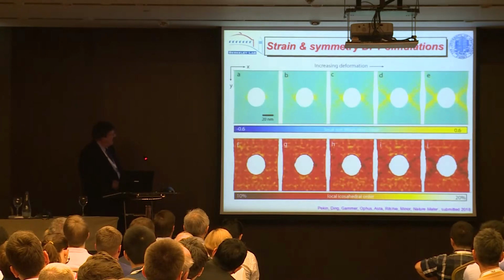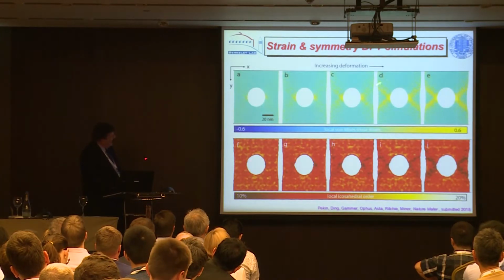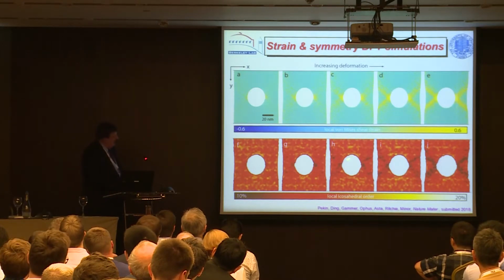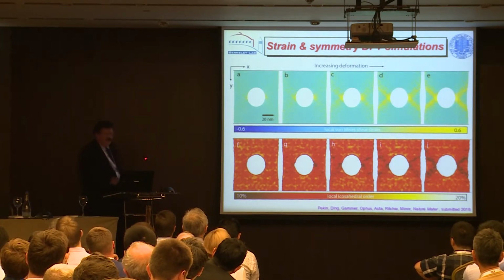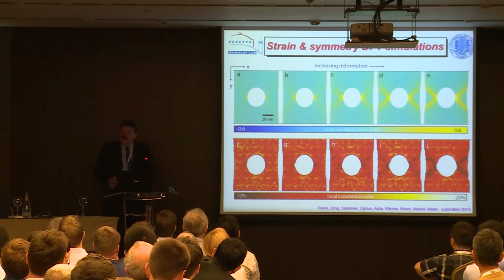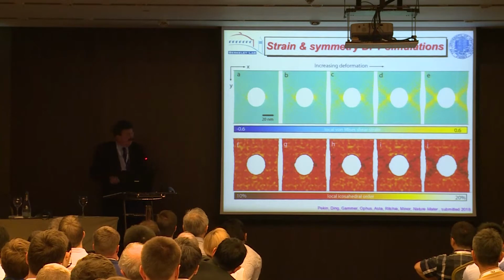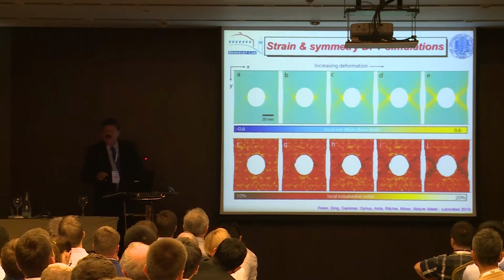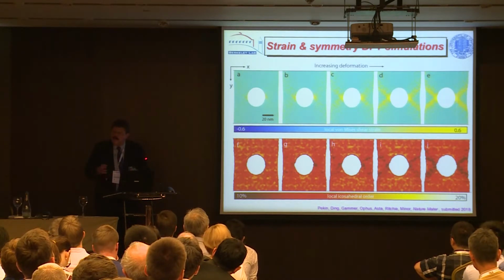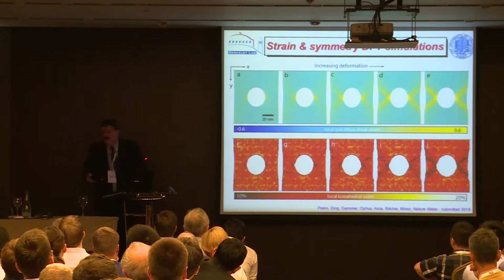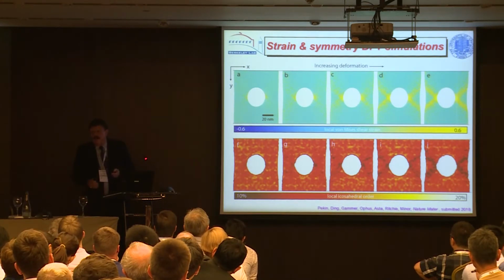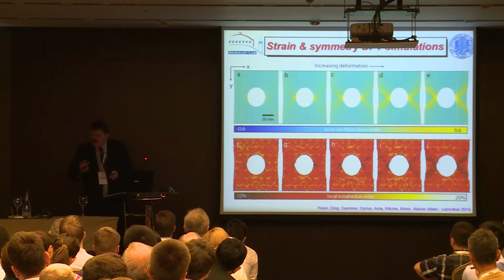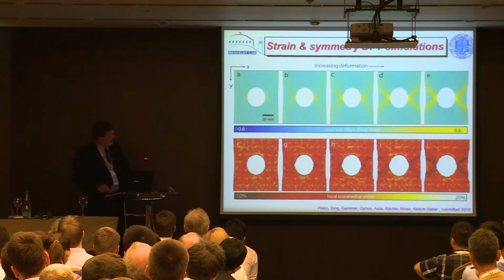So the tie-up here is that where we're having shear band formation can be associated with regions of less icosahedral, less stable local order. So it's, I mean, we're not there yet. This is kind of a chicken and egg argument here, but we think we can put the two together and get experimental verification that this is the essence of building toughness in glasses by generating less stable local order.